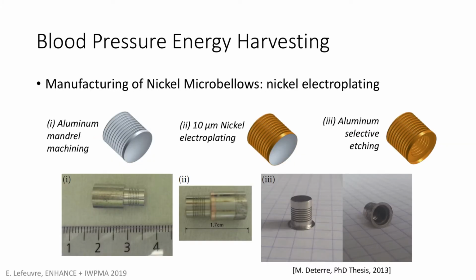So we started to investigate how to manufacture microbellows using nickel electroplating. Here is a description of the process. First, we machine a mold of the microbellows, and then we deposit a thin layer of nickel by electroplating. So it's a conformal deposition. And then we etch the aluminum mold, and we get our microbellows. You have here pictures of the mandrel, the mold, here the system with the nickel electroplated on it, and then the microbellows when it's released.